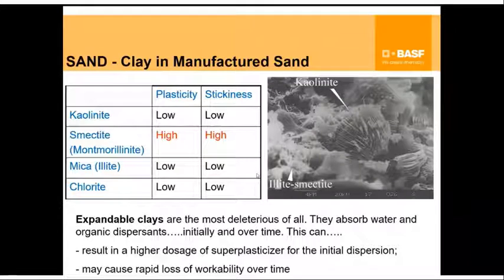And these smectite clays can increase surface area very significantly. And more surface area means that all of the chemicals that we are adding into the concrete are getting preferentially eaten up by the surface area of the clay, which means you're not going to see a lot of changes happening in the cement grains itself. Often what this means is that your dosage of chemicals goes up high to get any kind of desired plastic properties. This could also result in very rapid workability loss, again because of absorption of a lot of chemicals by these surfaces. And because of absorption of high amounts of water, these can also cause plastic shrinkage cracks when you have high amounts of clay.